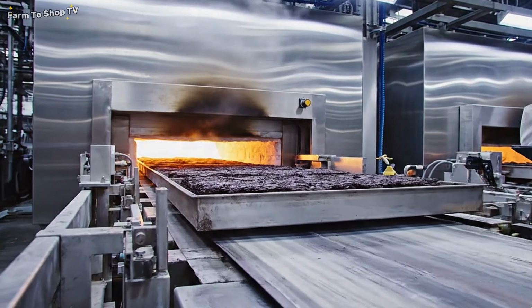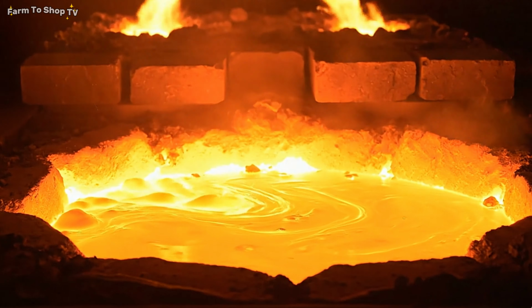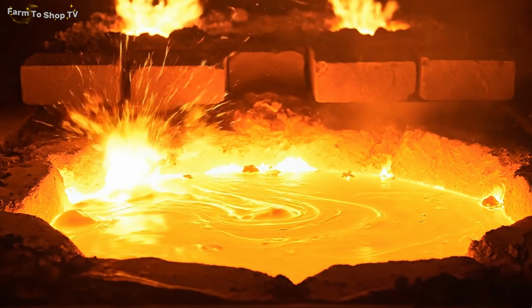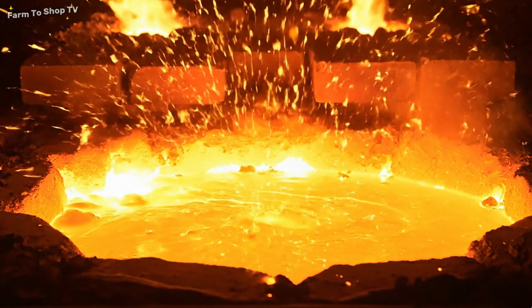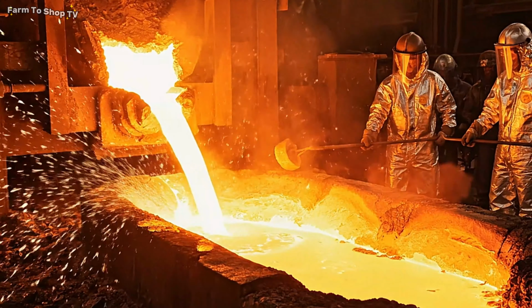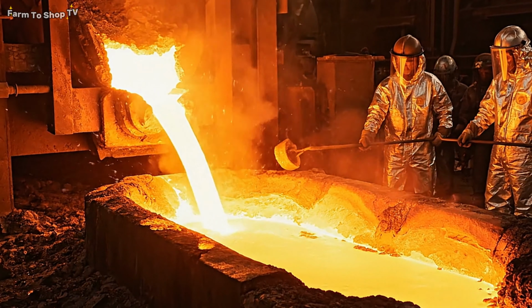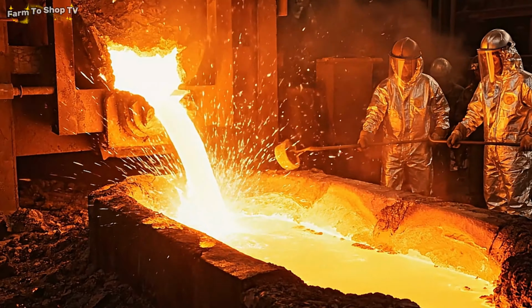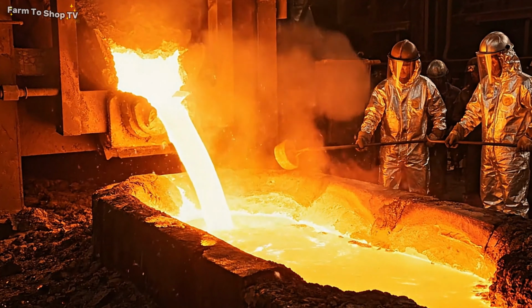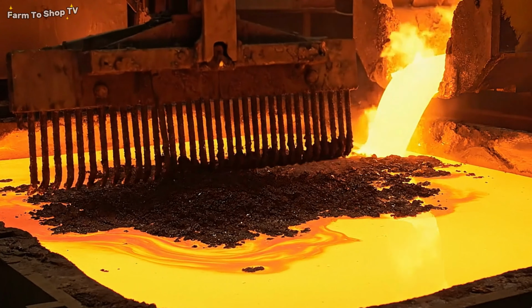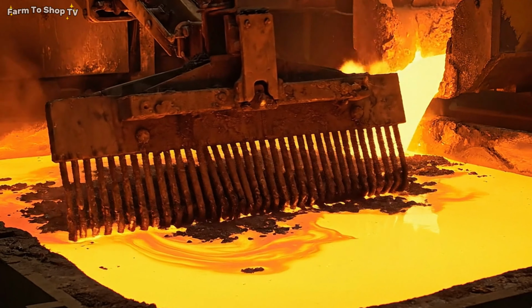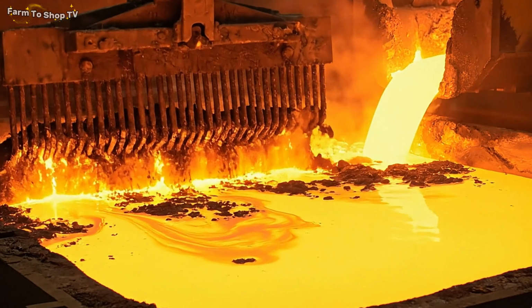The smelting chamber reaches temperatures exceeding 1,000 degrees Celsius, transforming raw ore into this mesmerizing molten gold. The smelting process reaches its peak as the gold, heated to over 1,000 degrees Celsius, is poured. In the slag separation basin, impurities float and separate from the molten gold.